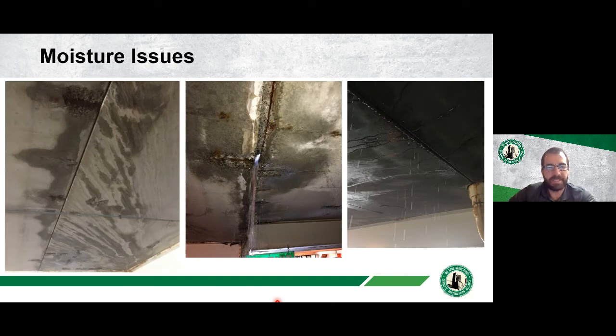Because this is precast slabs, there are joints between the slabs, and you can see there's water staining occurring there, so there's water transport between those slabs, which can allow for water to get into the post-tension sheathing as well. You can see here's actually water just running off through those joints and dripping through those joints. So, water getting into these strands is a major problem for this parking structure.